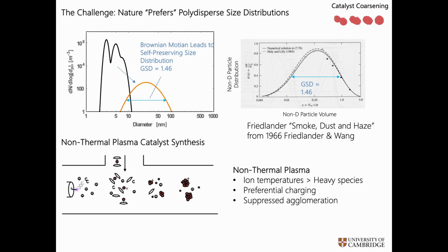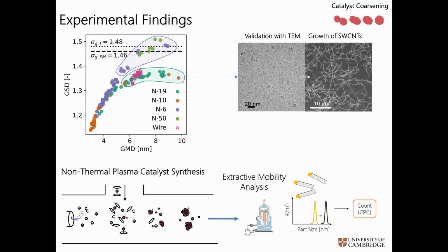So, that might induce things in your mind like entropy that is forming here, and we're losing information about what the initial structure was. And all processes basically go to this. And we need to fight this, basically. This is the enemy, in that it creates a very broad distribution of catalyst sizes. And we ideally would like to have the right size growing our nanotubes, and this is what we need to combat against. And so one way to do that is to suppress the collision rate between various particles.